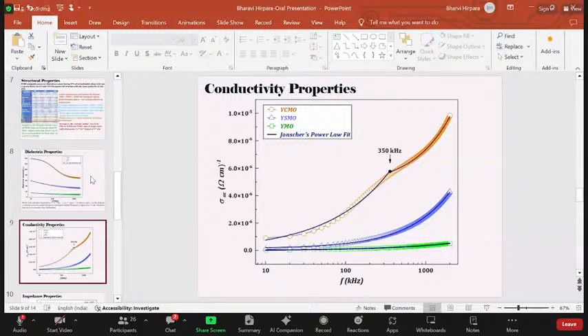So the ground state of all the samples is semiconducting at room temperature. The core of the crystallite is experiencing semiconducting nature. YCMO possesses comparatively lower size disorder as compared to YSMO, and YMO has no possibility of Mn4+ ion. Thereby, it is difficult to have Mn3+ to O2- to Mn4+ lattice formation, whereas a better assisted Zener double exchange lattice can be realized for the YCMO compound as compared to YSMO. So that is the reason.